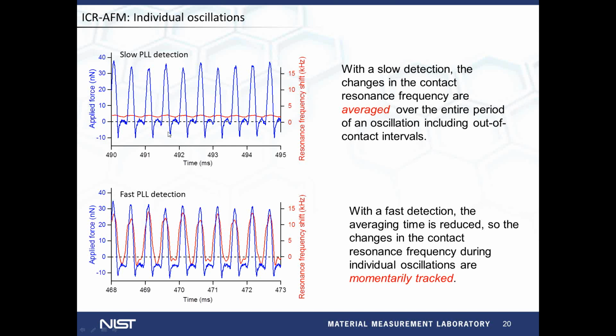With slow PLL detection, we see that the major shifts in the contact resonance frequency are within 1 kilohertz from the free resonance frequency, with no significant force dependence. However, with fast PLL detection, the resonance frequency responds with fidelity to the force variation during each oscillation. Again, this is because with fast PLL detection we momentarily track the changes in the contact stiffness and how this changes with the applied force. But this also points to the fact that only a three-dimensional characterization will be meaningful, as it is too complicated to separate the average contributions contained in two-dimensional maps.